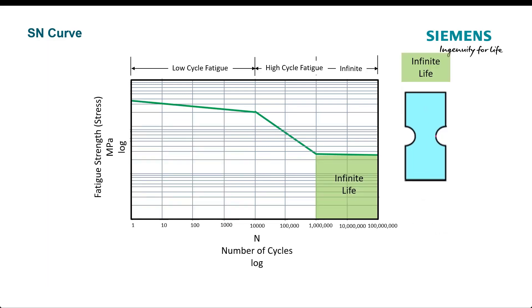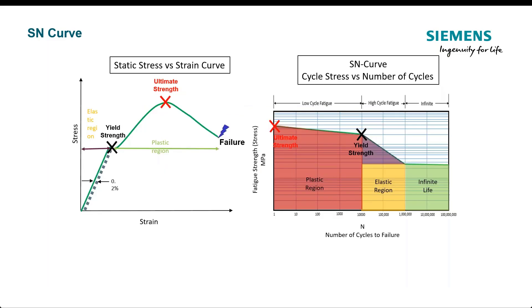And then we have the infinite life region. If we keep the stress below this level, we never accumulate damage. Just be real careful about the infinite life, because the theory also says that if I go above this level one time, one time, then I have damage down here. So that's the infinite life region. Not all materials have an infinite life.